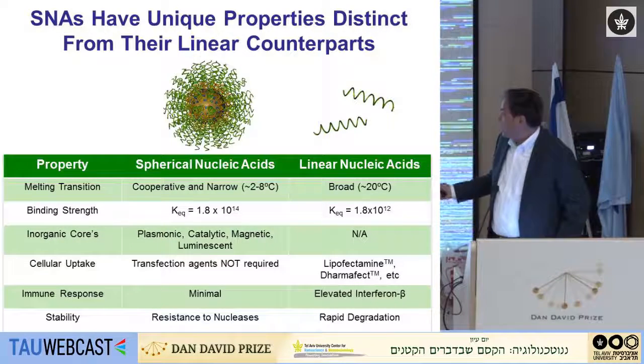If I look at the subsequent melting properties, normal DNA melts over a very broad temperature range. These types of structures melt over a very narrow temperature range. You can get them down to a single degree. Why is that important?